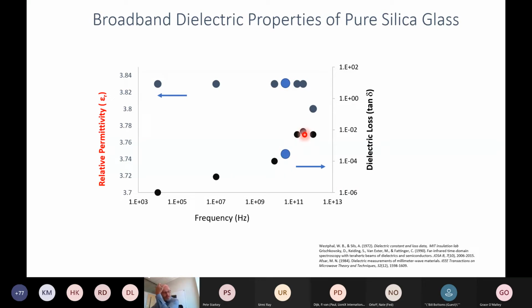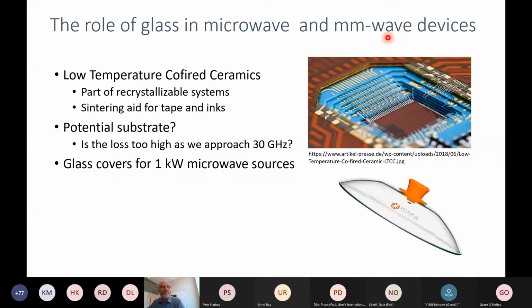And so you can see this peak here. And this peak then is very interesting because normally with oxide materials, we don't really see peaks in this frequency range. We either see peaks well above it due to ionic polarization or well below it. So glass is a pretty interesting material. It's also very interesting for devices, right?